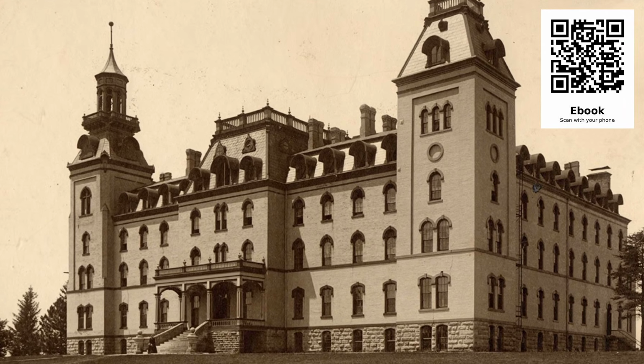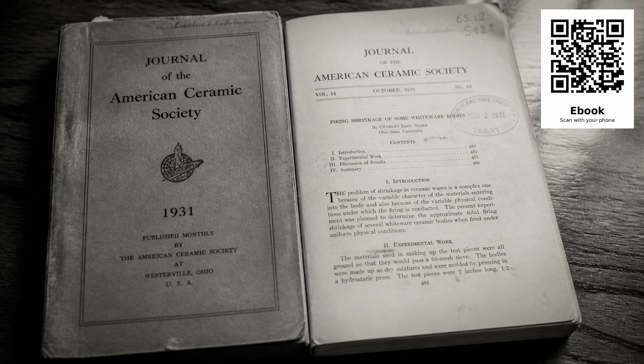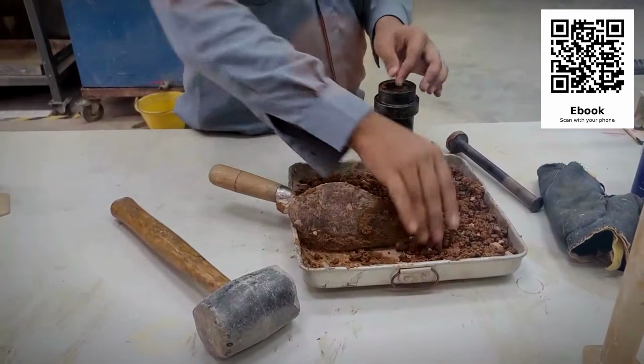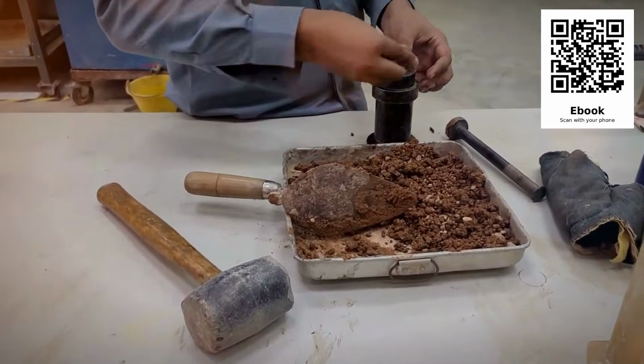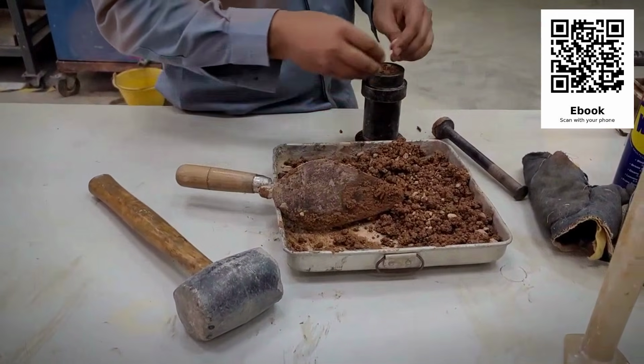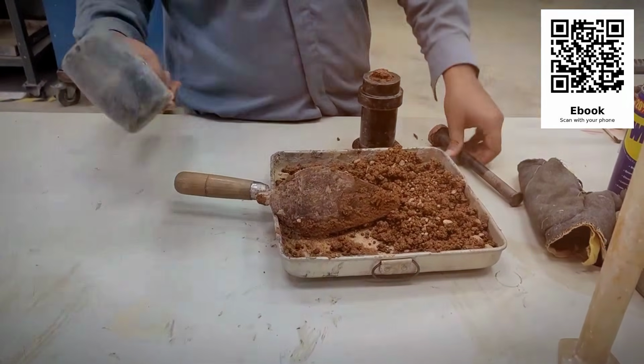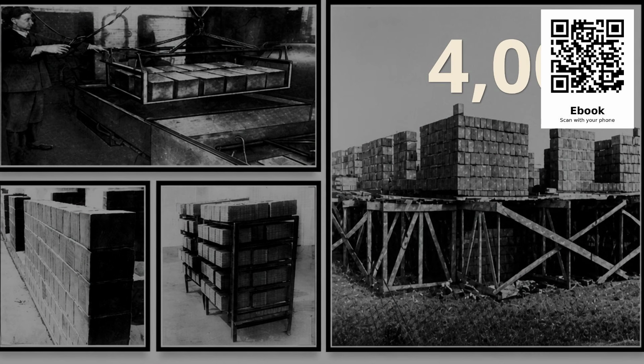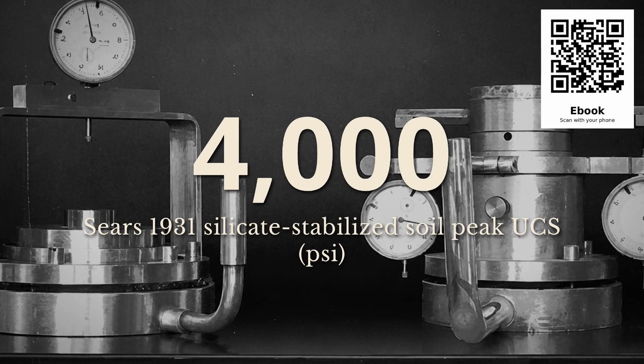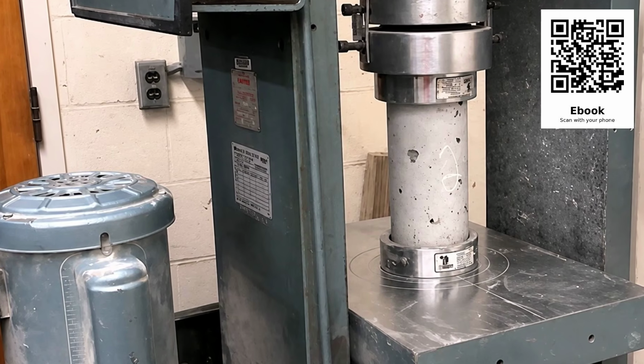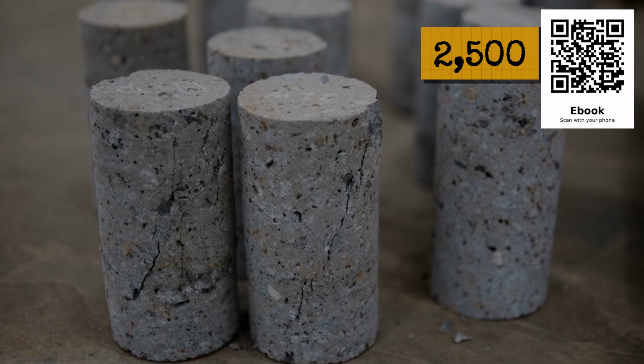Let me tell you about a man named Charles Earl Sears. Sears was a soil chemist working out of Ames, Iowa in the late 1920s, and he published a paper in 1931 in the Journal of the American Ceramic Society detailing the compressive strength gains of silicate-treated clay soils. His findings were remarkable. He documented untreated clay with a compressive strength of around 200 pounds per square inch, reaching, after silicate treatment and full cure, compressive strengths above 4,000 pounds per square inch.